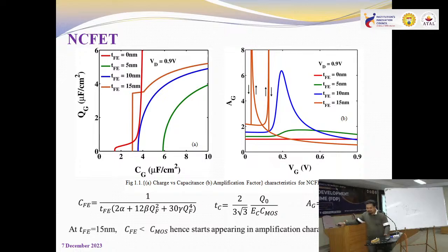So that is what I am telling. At TFE equals 15 nanometers, there will be hysteresis. Both other two cases are fine. No problem with the other two cases. The problem arises only at 15 nanometer.